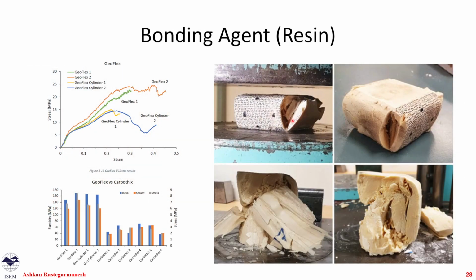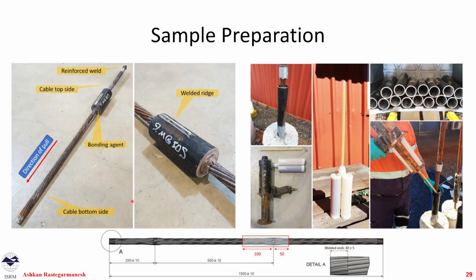So the other thing was change of resin. We changed to a different resin. This resin was called Geoflex, from the same company, Minova. And this one, as you can see, had a different type of failure. It's like a barrel type failure, like strain hardening, it wouldn't even fail. So we even had to go up to like 2% strain to get our UCS value for it. You can see the difference between the Geoflex and Carbothix, which was the previous resin for the larger scale test. Both our UCS and our Young's modulus are much different between them.